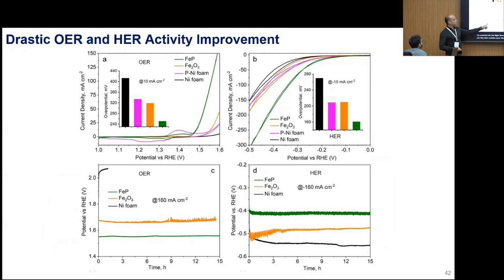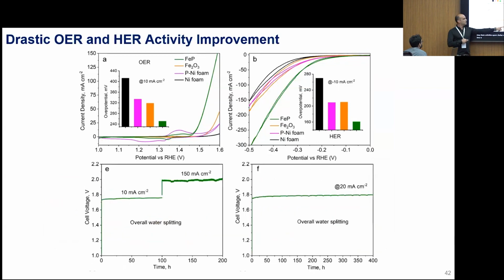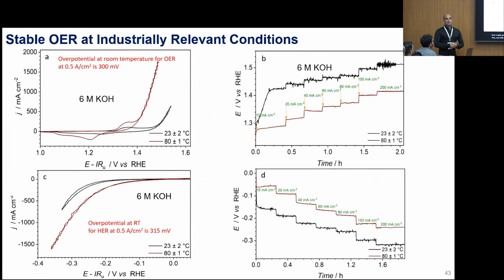And if you look at the performance over time, it's quite good, just a few hours, that looks for hundreds of hours, very, very stable. So these results were very encouraging. So we went into looking at industrially relevant conditions, which usually are not at room temperature, in black, but at 80 degrees, and with very high alkaline conditions, 6 mole of KOH. And you can see here, we only need a very small overpotential of 300 millivolt to produce 0.5 amp per square centimeter. Right? So this catalyst is excellent.